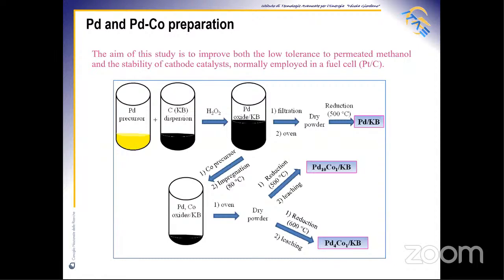30% palladium and palladium cobalt alloy supported on a carbon, that is Ketjenblack in this case, were prepared using the sulfite complex route. An appropriate amount of Ketjenblack was ultrasonically dispersed in water and then mixed with the palladium sulfite acidic solution. Subsequently, hydrogen peroxide was added to decompose the sulfite complex with the formation of a colloidal suspension, that is palladium oxide on Ketjenblack. Hence, the suspension was filtered and copiously washed with water and dried.